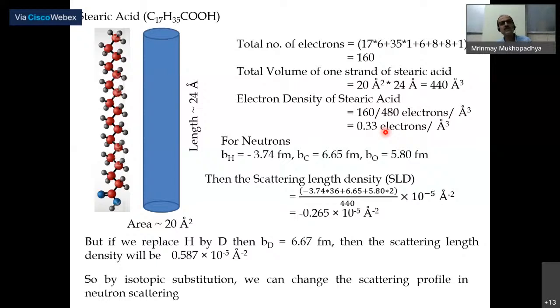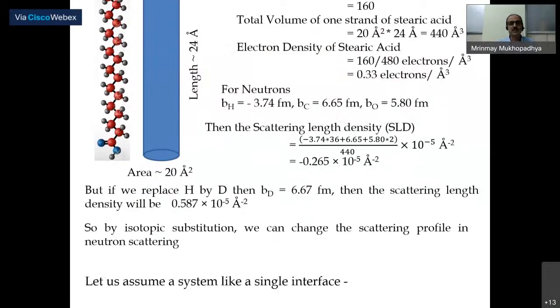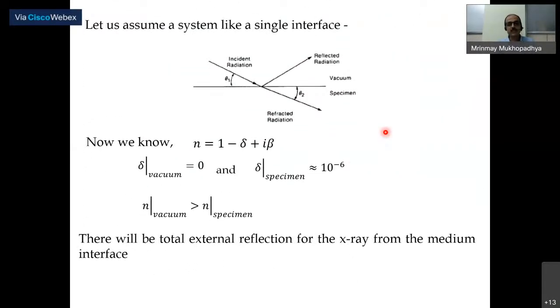So you are not actually changing your scattering much in X-ray, whereas in neutrons you are changing the scattering hugely. And that is one of the main advantages of using neutrons for biomaterials: with isotopic substitution, you can determine more specific information about your sample. That is basically the part I want to say, that each probe has definite advantages and you like to use that probe for them.